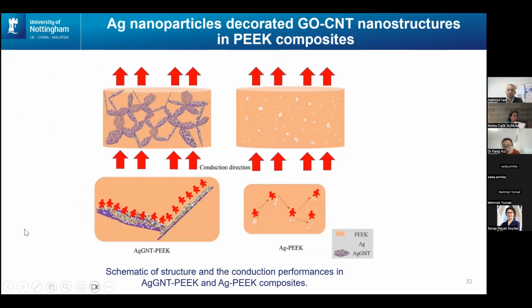We tried to understand why this happened. For silver reinforced PEEK, the silver particles are randomly and separately dispersed in the matrix, so it's very difficult for electrons or phonons to travel. But for silver-coated GNT reinforced PEEK, there is an expressway for both electrons and phonons to travel. This is why the thermal conductivity improved by 50%, while the electrical conductivity improved by 10 to the order of 9 times better. This is something we can always think about, and maybe transfer to other material systems.